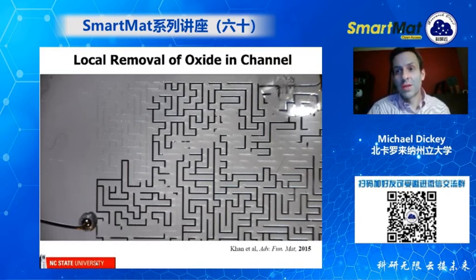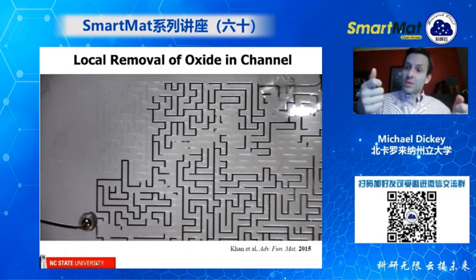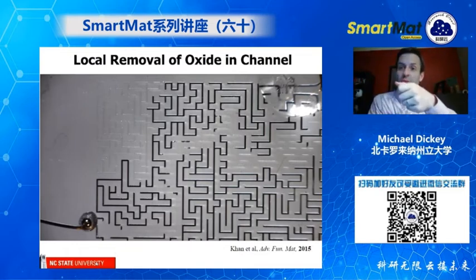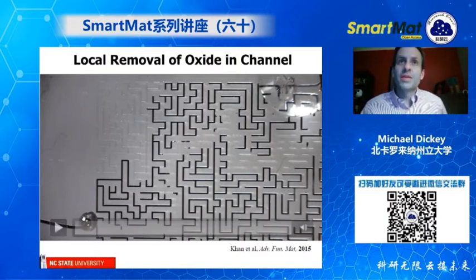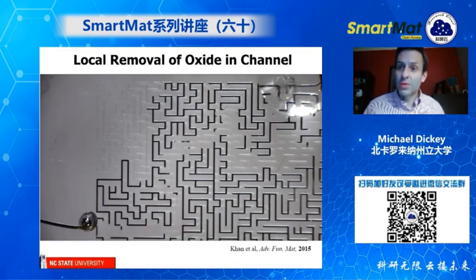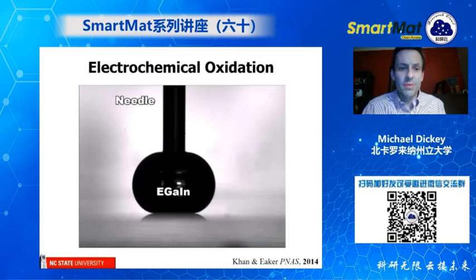But the real challenge from a physics standpoint is how do you get the metal to go back inside the channel? Now, if you just simply took the 2 electrodes and switched them, that might be an intuitive approach. But the problem is, instead of reducing the oxide, you would actually deposit the oxide. You would oxidize the surface. And so nothing should happen. And so we did this experiment.